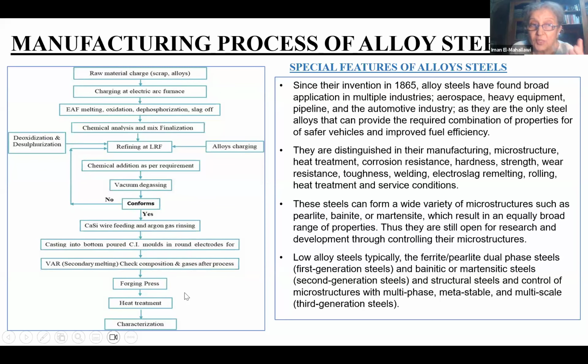So we have one challenge during the melting and production process, and the other challenge is during the heat treatment. If the heat treatment is not controlled, you do not get the properties that you opt for. Of course, the manufacturing and the heat treatment would be manifested in a microstructure, which makes us reach the properties that we are looking for. And that's why we need to talk about microstructure, chemical content, and heat treatment procedure, because you can never get what you want without controlling the microstructure, which is the main phases we know: pearlite, bainite, martensite, ferrite, duplex, whatever. All this has to be achieved.